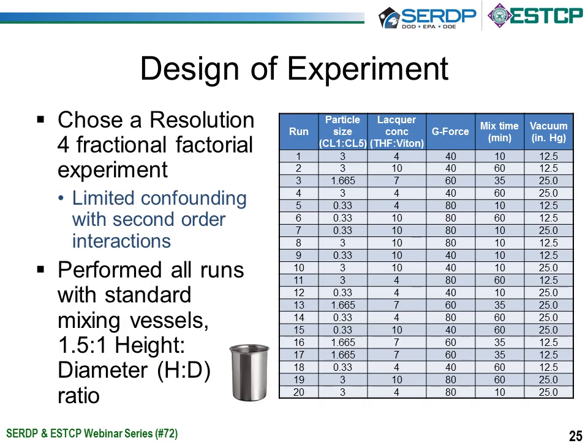So the design of experiment that we chose was a resolution 4 fractional factorial experiment. In this, we had limited confounding with second order interactions that could be resolved. We performed all runs using a standard mixing vessel, which is about a 1.5 to 1 height to diameter ratio.